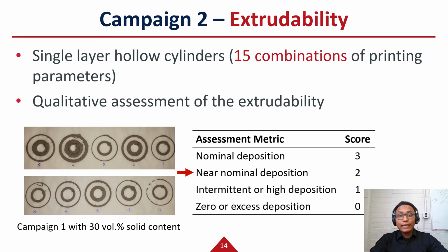Here, we qualitatively evaluated the extrudability of the material. You can see the assessment metric here. For 30 volume % solid content, you can see that we had nominal depositions for part number 14 and 15. But we had excess deposition for part number 4.